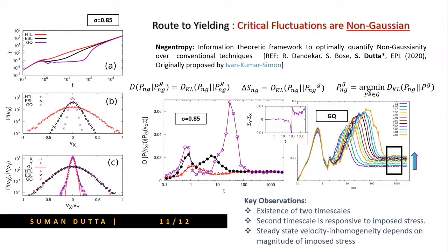Here for the GQ case we see that there are 2 prominent time scales when this non-Gaussianity becomes significantly high. There is a first time scale around this point which is not very significant. So, there exists a first peak, and the second peak appears somewhere close to this point. For the ESL we see that these 2 peaks are there, but the difference between them is less. For HTL these 2 peaks have merged and become 1.